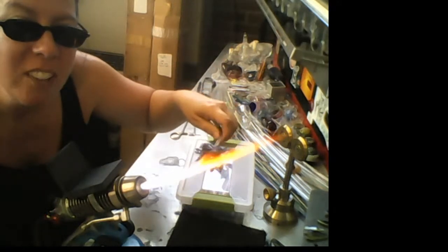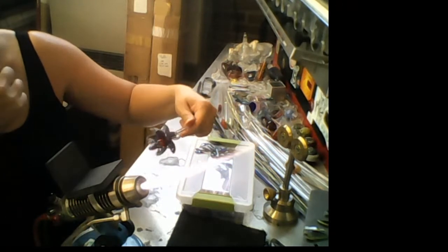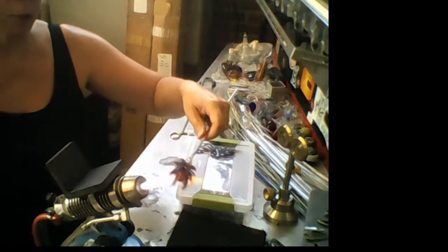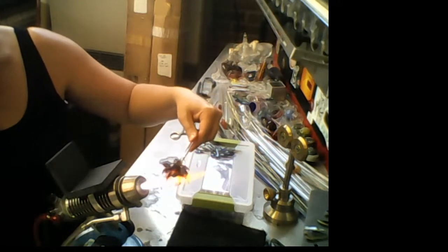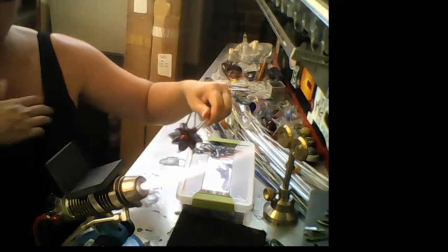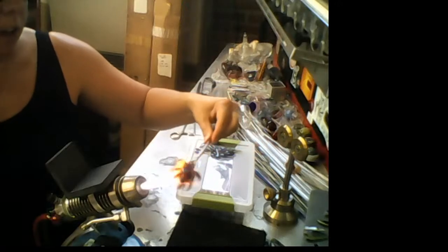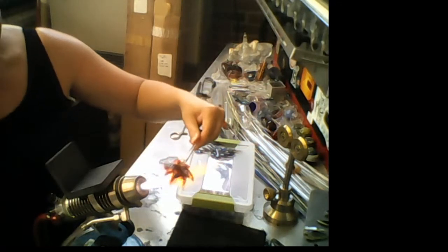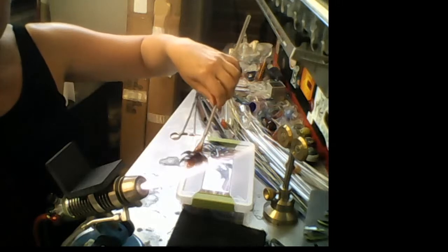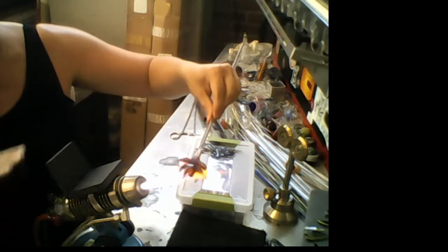Marilyn Wiska says, was the color in the glass or is the heat creating the colors? That's a really good question. So some of this glass that I've used has a combination of silver and germanium in it. And when glass that has the silver and germanium is exposed to a high oxygen ratio, the glass will actually start to change colors. So kind of a pink, purple, magenta comes to the surface. Which is really cool. Now, not all colors do that. Most do not do that.